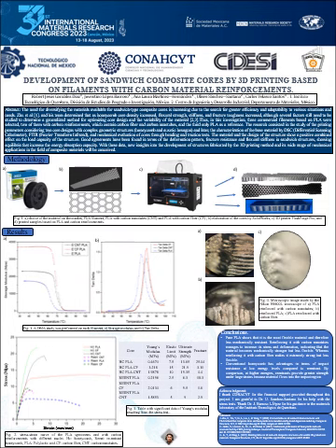The following is a stress strain plot which indicates that adding carbon nanotubes or carbon fiber to PLA can improve its mechanical properties, making it stronger and less flexible, depending on the shape and amount of reinforcement used. The values obtained by the graph were placed in the table. From this, we can understand that a higher Young's modulus implies greater stiffness and less deformability, while a lower value implies less stiffness and greater deformability.